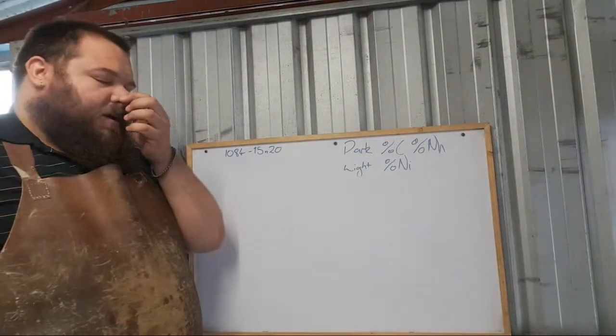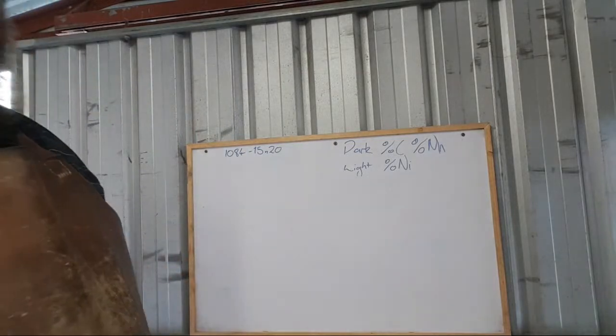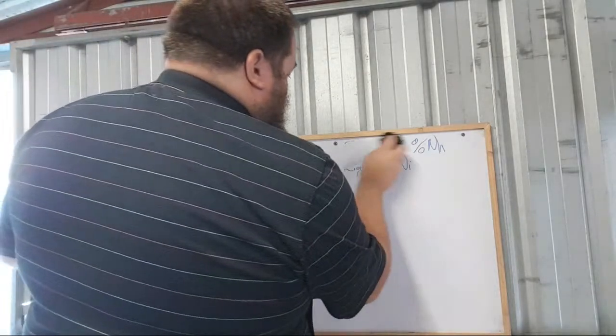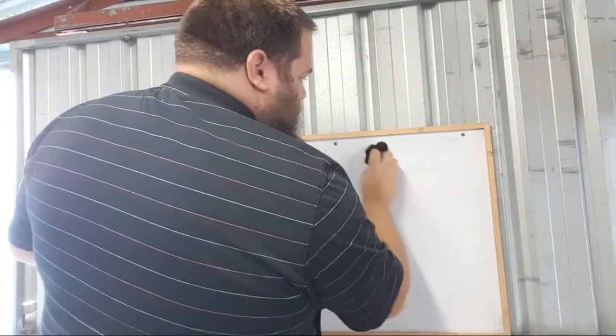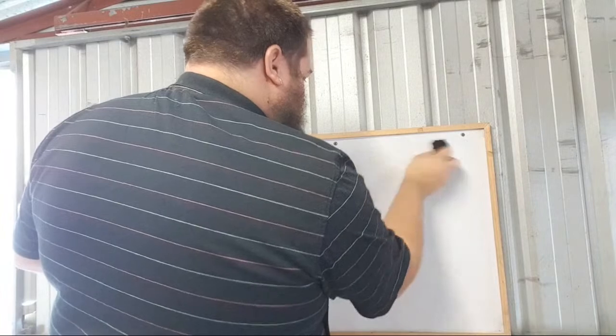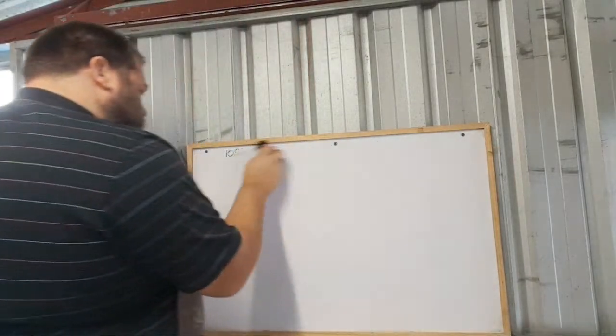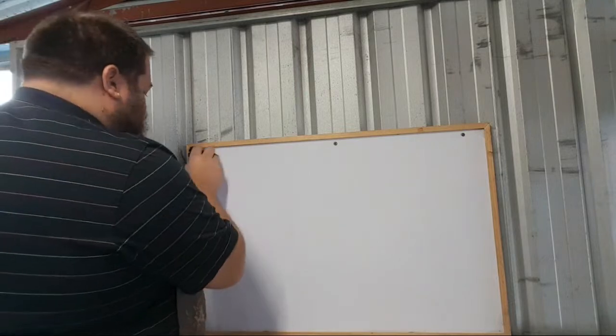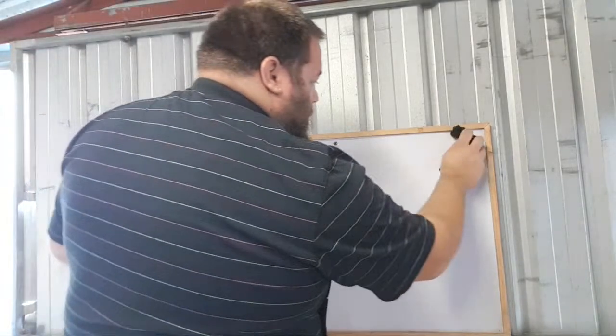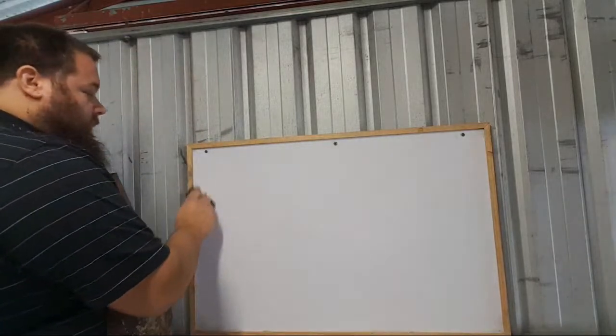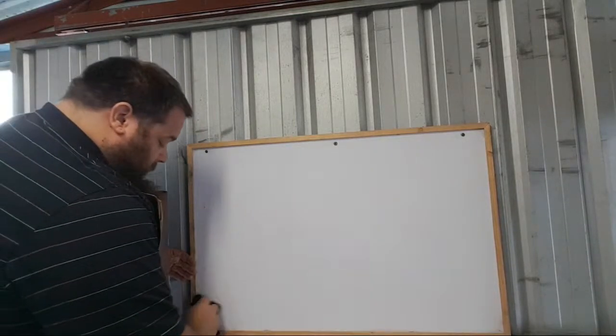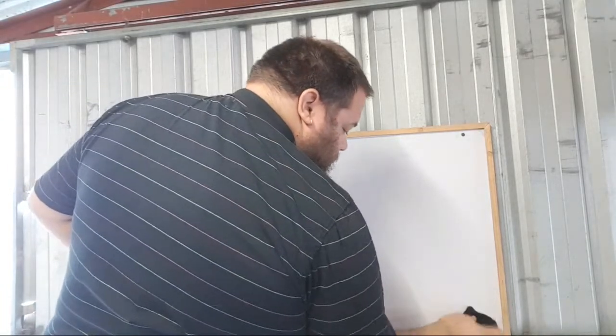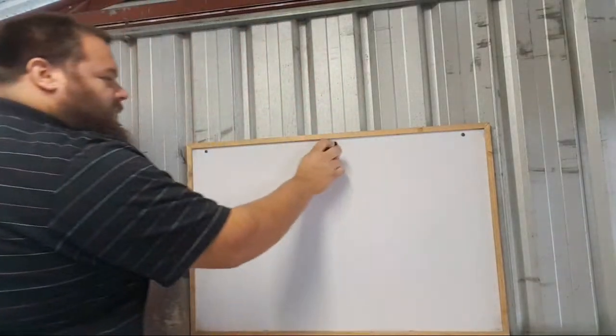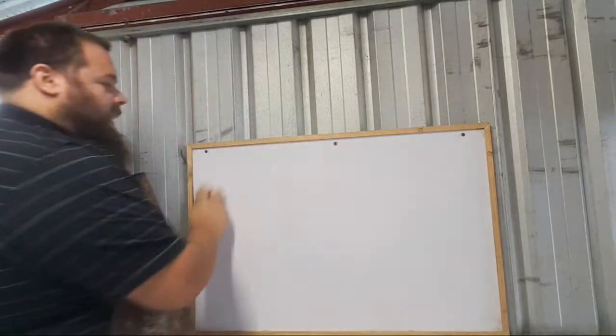Yeah, so leaf spring steel normally does not like to weld very well. So just take it with a grain of salt. You obviously can weld most steels, even stainless. Although if you're going to weld stainless steels, you have to completely seal the billet. There is no way to use flux on stainless that will work. Stainless does not weld in an oxygenated environment, even a slightly oxygenated environment. It needs perfectly sealed billets.